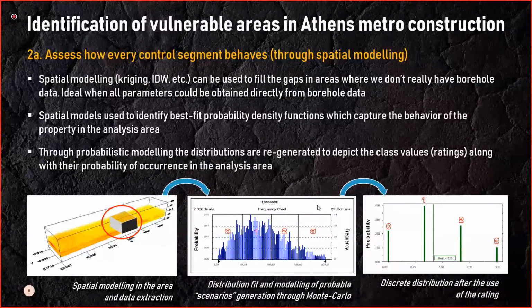So the spatial analysis is the next step, and the 3-dimensional spatial analysis is done by GIS software using the Kriging algorithm or inverse distance weighted methods, directly using the borehole data. In this step, the values obtained from the spatial modeling are extracted and form a distribution function of the model parameter itself, which actually mimics the behavior of the parameter. Through the probabilistic modeling, these probability distributions are then regenerated to depict this time the class values, using discrete probability and employing the threshold values that we saw earlier in the rating. Then we have information about what class to expect and what is the probability of occurrence.